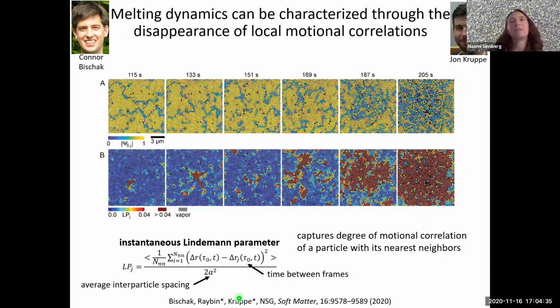And John adapted the Lindemann parameter so that we could keep track of individual particles as a function of space and time. So in particular, sort of frame to frame, all at once. And this is basically a parameter that's capturing the degree of motional correlation of the particles with their nearest neighbors. So you can definitely see here that the persistent fluid phase develops, especially in these latter three frames. That's the maroon color above a given threshold.